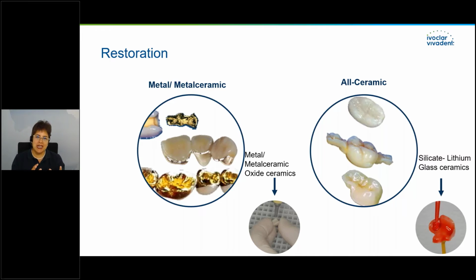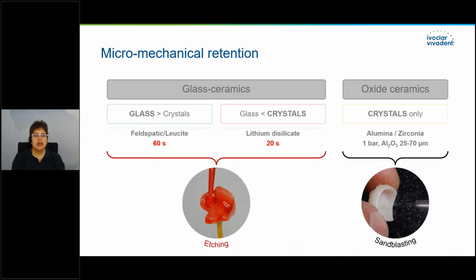But depending on the type of glass ceramics, we need to etch differently long. Many of us are not aware of this important point. Let's speak about glass ceramics. Here we see that we have two different groups. Both contain a glass phase and a crystal phase. One group, where we have feldspathic glass ceramics, they have higher amount of the glass phase. And here we need to etch with hydrofluoric acid for 60 seconds. The second group, which is lithium disilicate, you see that here we need just to etch 20 seconds because we